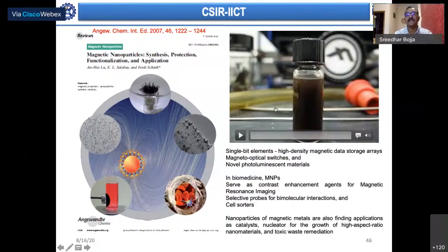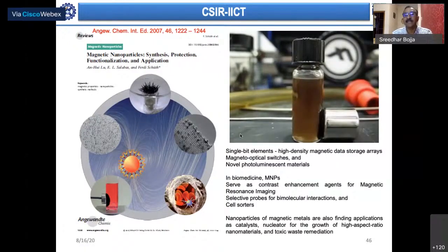The advantage of using this catalytic material as a catalyst is that separation from the reaction mixture becomes very easy by just placing a magnet next to it. These particles are very small, so to separate them from the reaction mixture you would have to centrifuge them using a very high revolving centrifuge, which is expensive, and in the process you lose some of the material. But with this magnetic material, separation from the reaction mixture becomes very easy by just placing a magnet next to it. That is why we started working on magnetic nanoparticles.